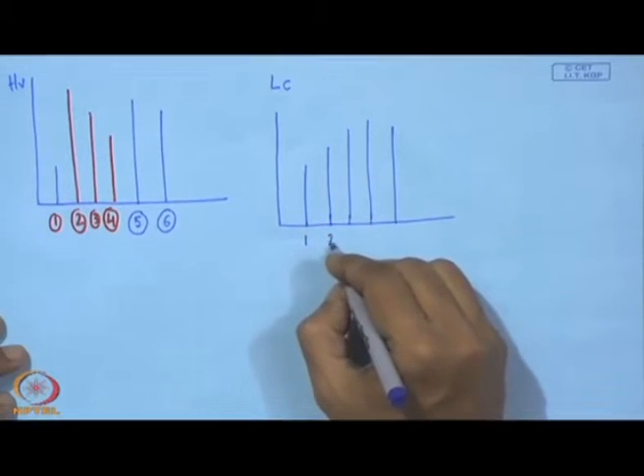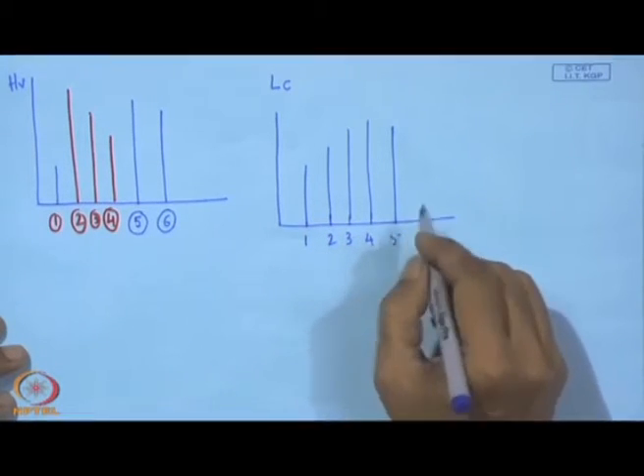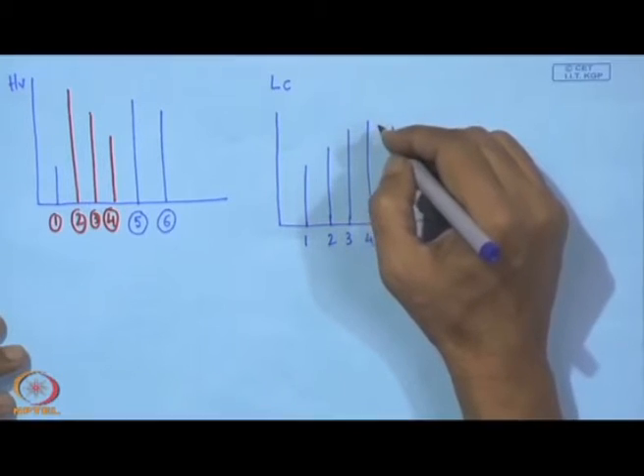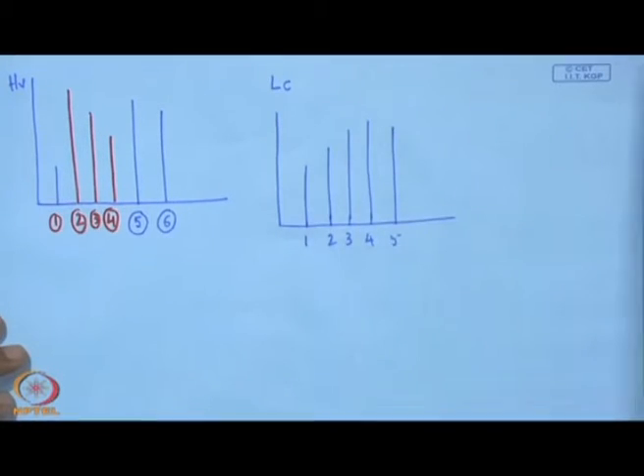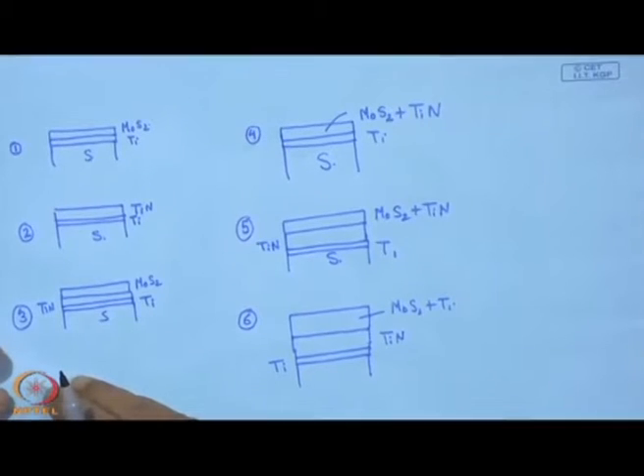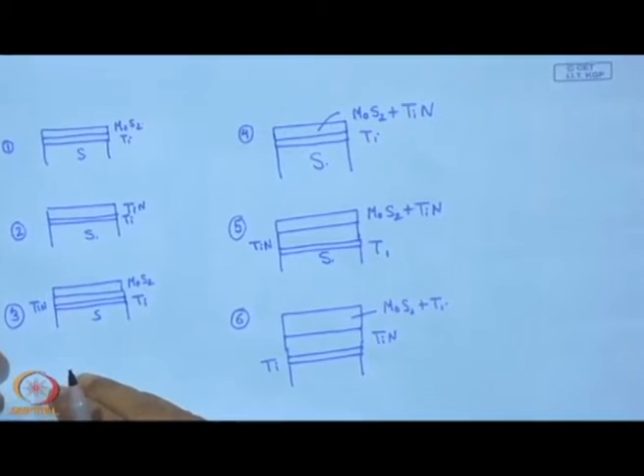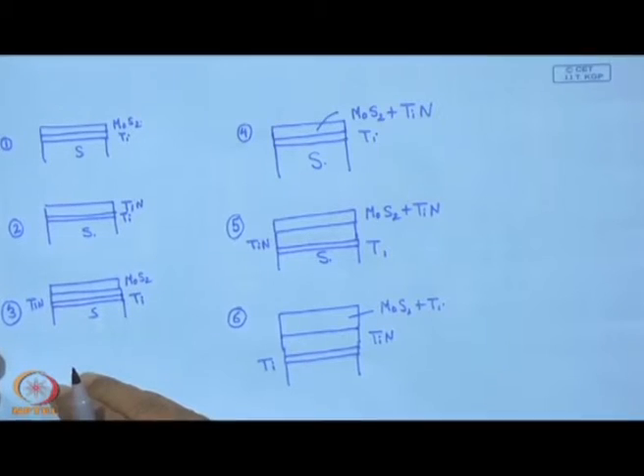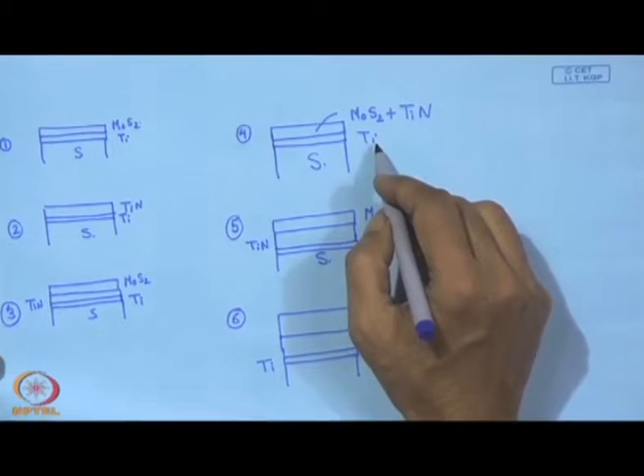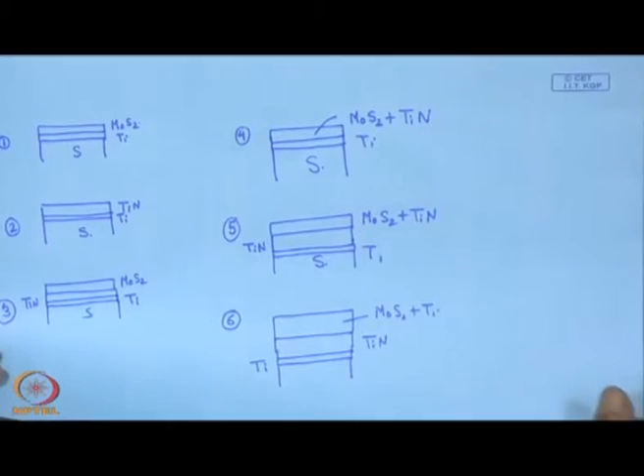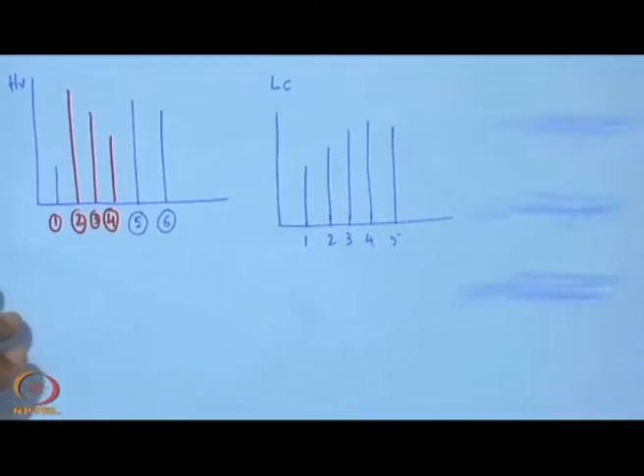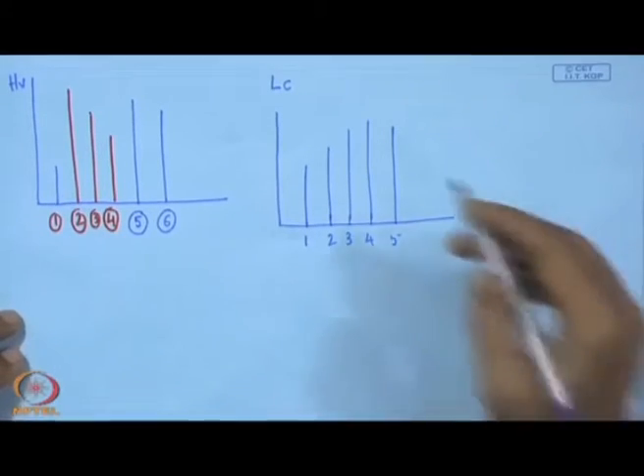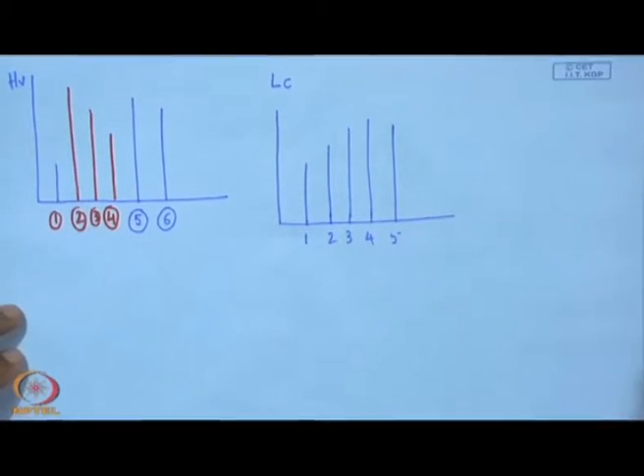This is 1, 2, 3, 4, 5, and this coating, that means the coating with this architecture of MoS2 TiN at the top, and with a coating interlayer of TiN, gives a good adhesion, and this is actually the value what we can see here. Now comes a very important thing.